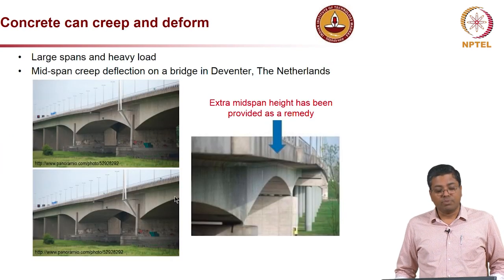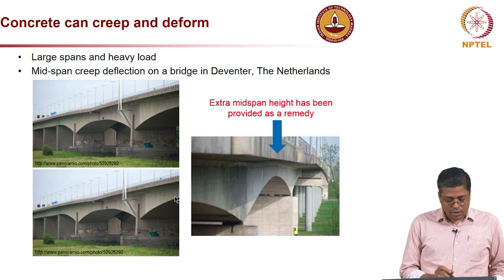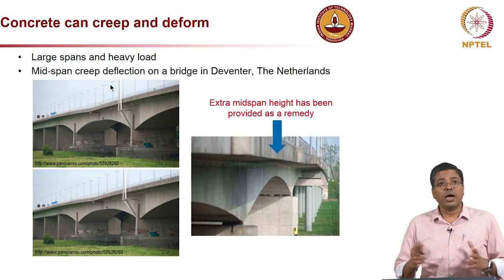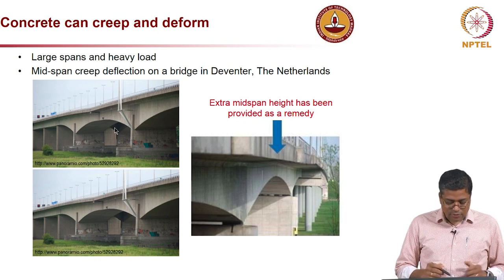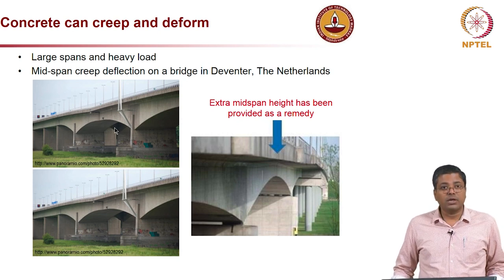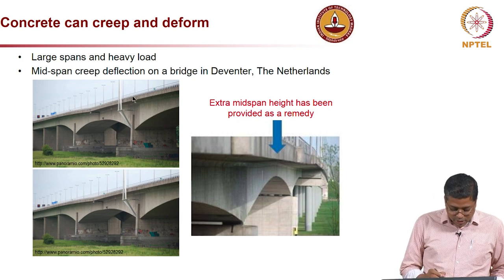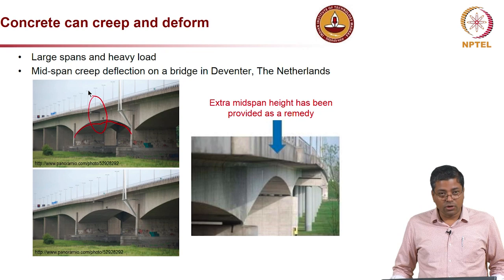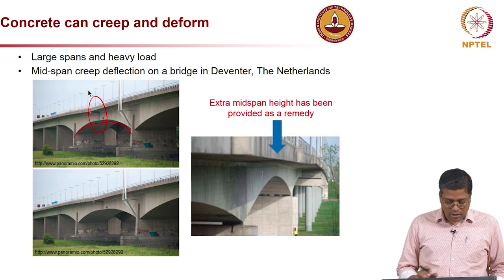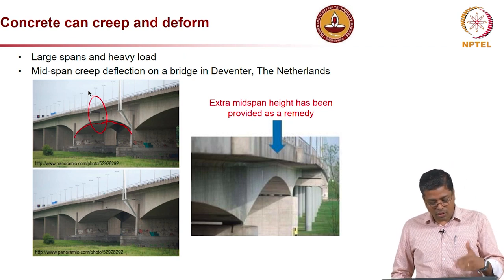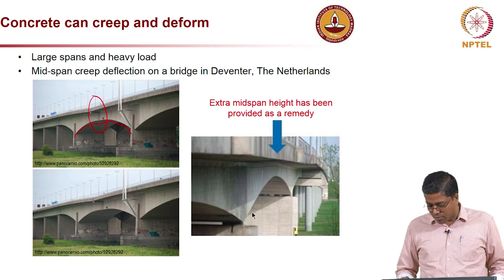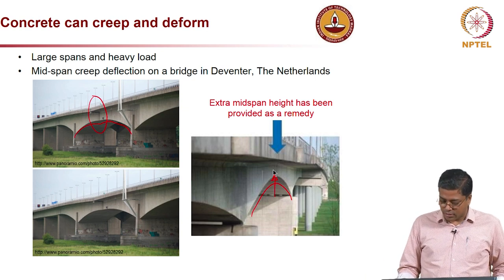Now, concrete can creep also and deform, and significant deformation can be experienced. In this case, you have a large span and heavy load. You can see the size of this concrete, and the dead load of this particular bridge is very high. In this picture, as you see, you have a dip at the bottom here. So, there is a significant depression or deflection at the center span, which is an indicator of significant creep, because that deflection happened over a period of time. As a repair procedure, they lifted up the center portion, so the mid span was raised a little bit and repaired, so that vehicles could drive without a dip on the concrete.